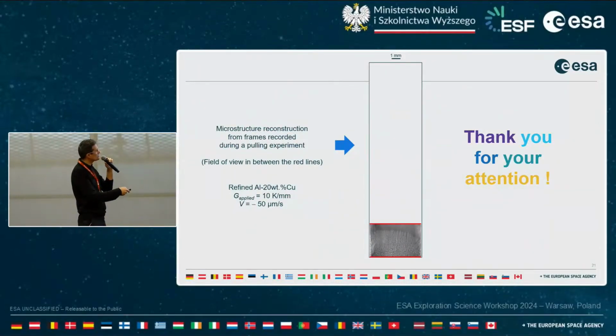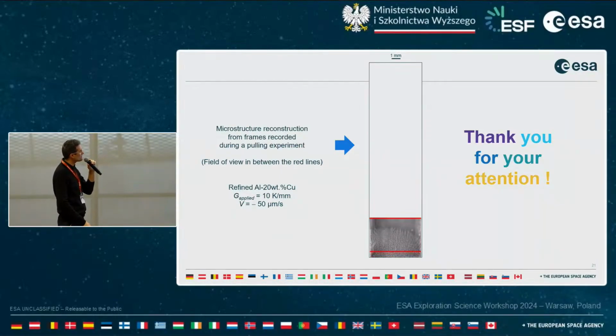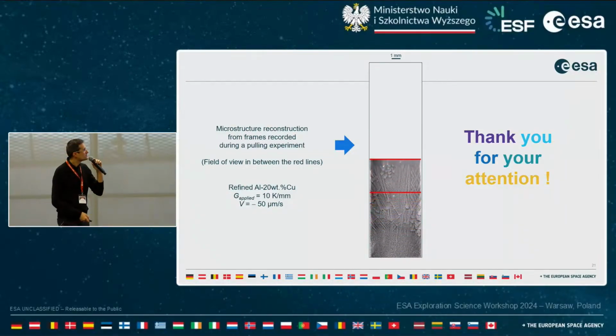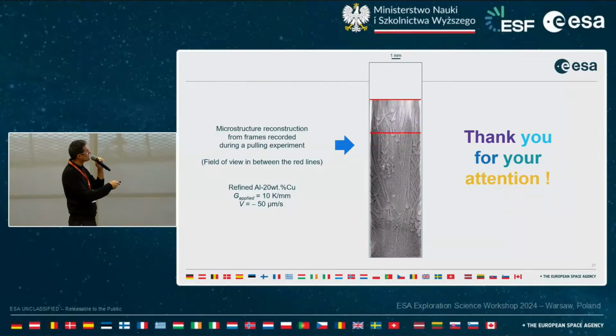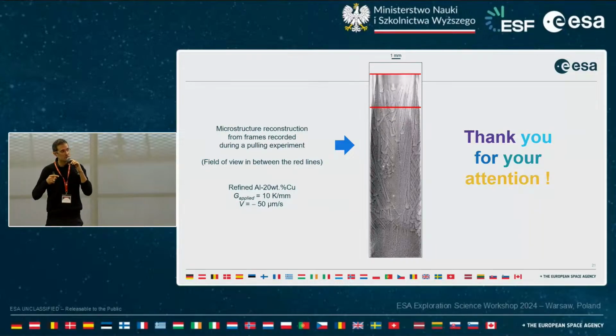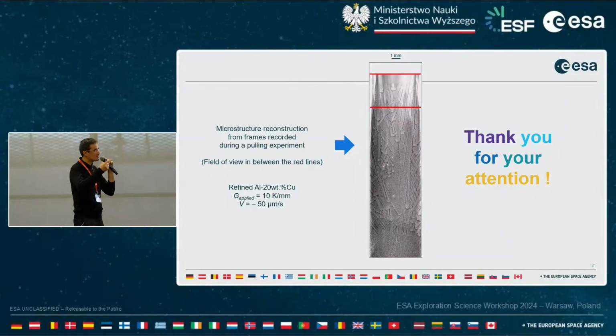I would just like to finish with a nice video, because this is what's nice with in situ imaging. We took a pulling experiment, and using a trick, we changed the reference frame just to show that with a pulling experiment, we can have an image of the whole solidification of the sample. And since we plan to cycle the samples, remelt them and solidify them again, it would be useful to have an overview of the whole sample using such an image processing trick.